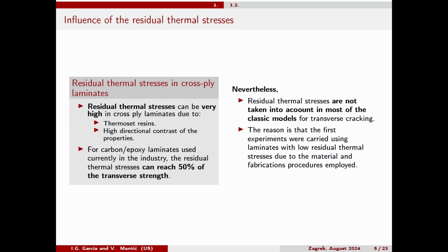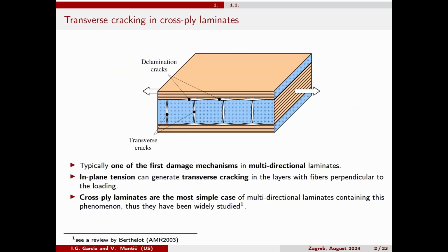But they don't take into account the residual thermal stresses that we can find in this kind of laminates. If you go back to these slides, you can imagine that if we fabricate that in an autoclave at a high temperature, and we have a different coefficient of thermal expansion in the different directions of the lamina, when we decrease the temperature from the curing temperature to the service temperature or the test temperature, the compatibility between the different layers is going to be imposed, and in this case, the stretch and the contraction between the different layers are going to be different, and that's going to generate some kind of residual thermal stresses inside the layers.